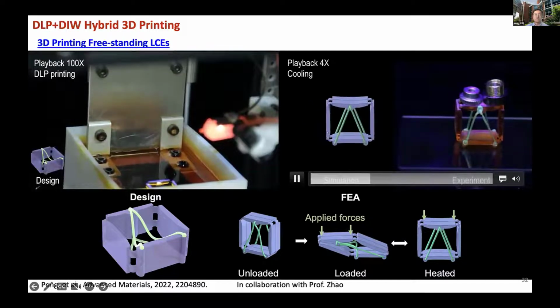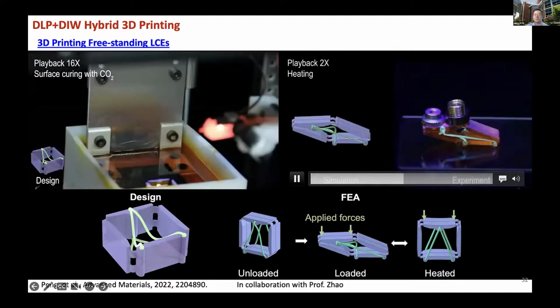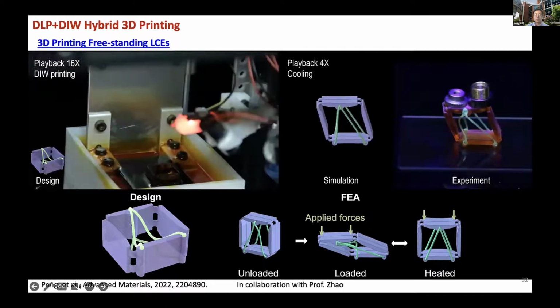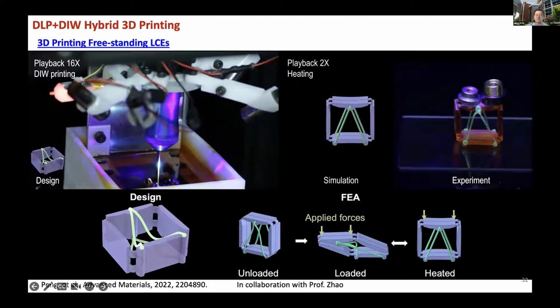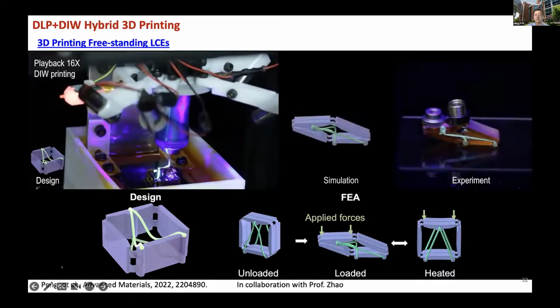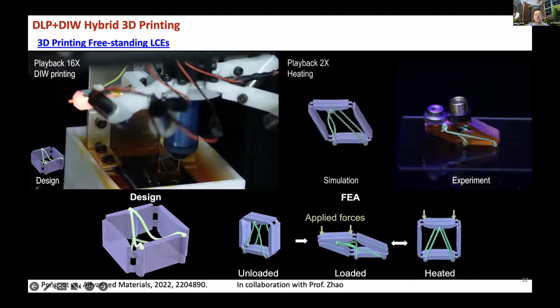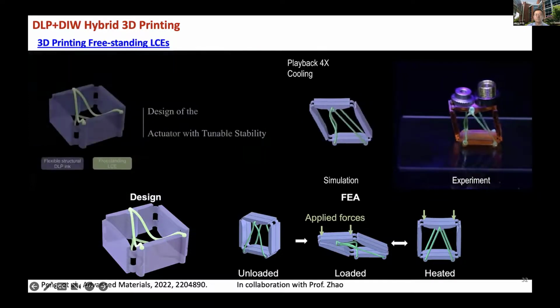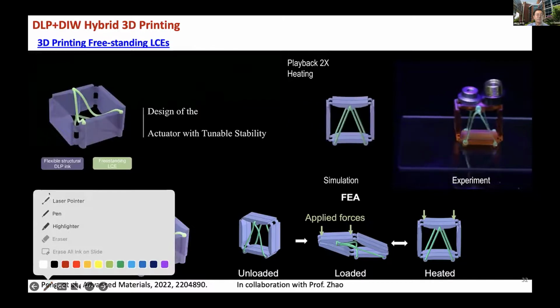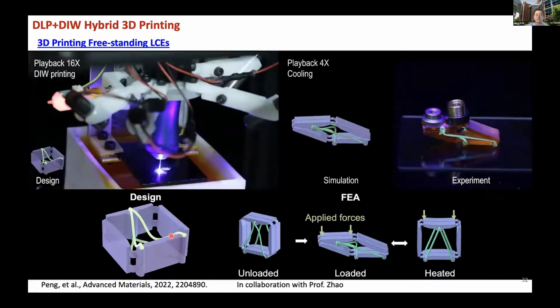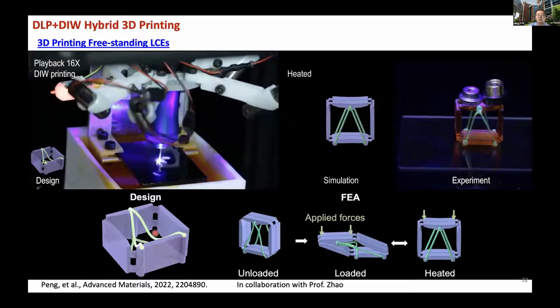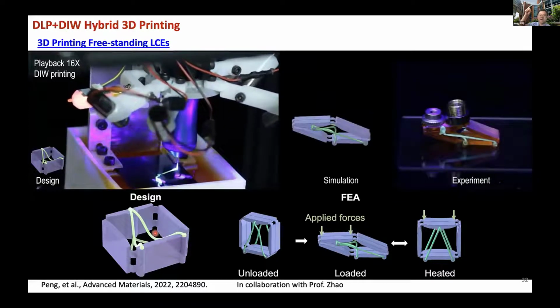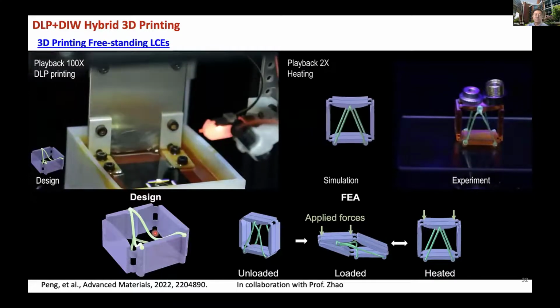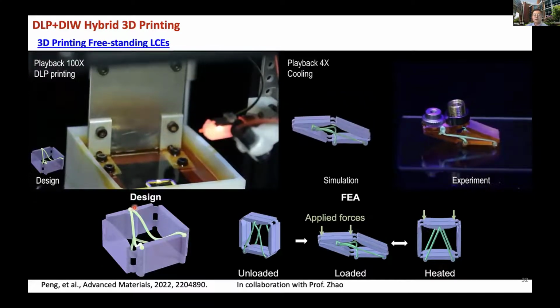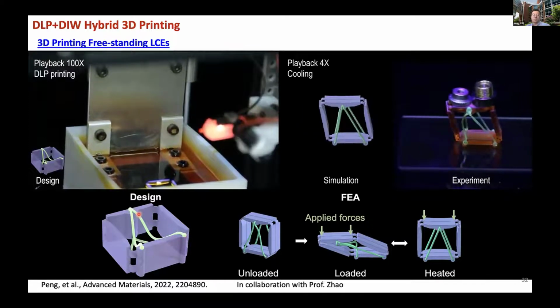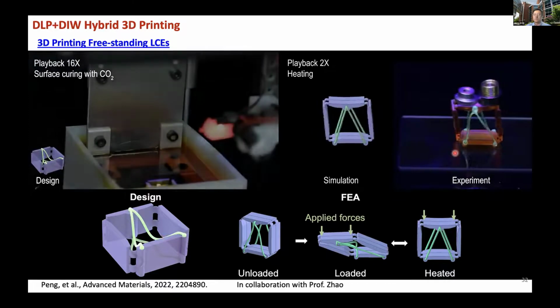So in this case, we also print this kind of liquid crystal elastomers to it. So as we heat it up, the liquid crystal elastomers shrink such that it increases the stiffness of the structure, so makes the structure stand out. In this case, it's very interesting. You can see this wire here is actually very loosely contacted. So what Shiri did, he printed not in the plane, he actually printed up. And after printing, he dropped it down. So this length would be longer than this one, such that when you print, it's still kind of a very loose structure. Then when you heat, it will just pop up.